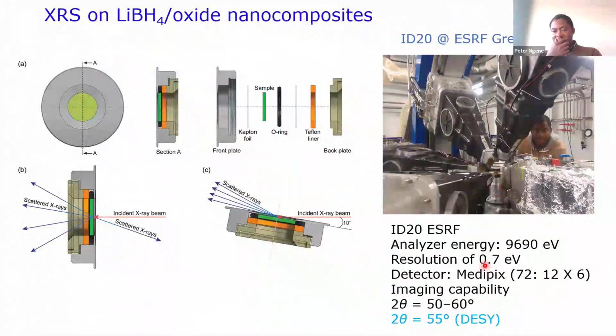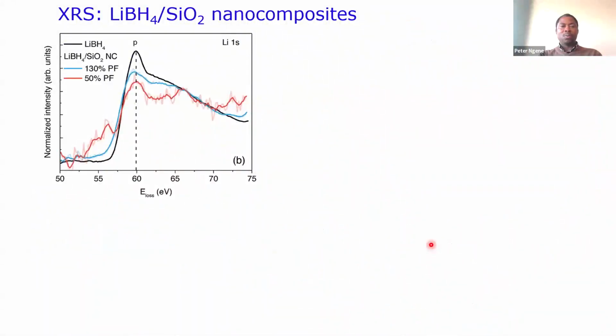So now we spent time really making a nice in-situ cell this time around, to make sure we don't have any oxygen leak, so that what we observe is what we have. Then we went to DESY to do this measurement. And then, we also went to ESRF first, at ID20, where Christophe Sahle and Alessandro Longo work. We did this experiment with DESY as well. And actually, we spent 5 years trying to figure this out because we wanted to be sure that the result we get is not a result of beam damage or any oxidation. That's why it took about 5 years for us to get this data.